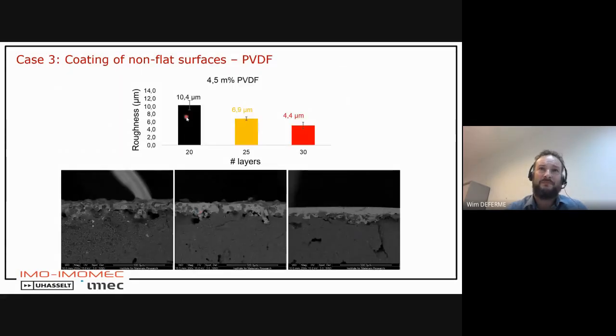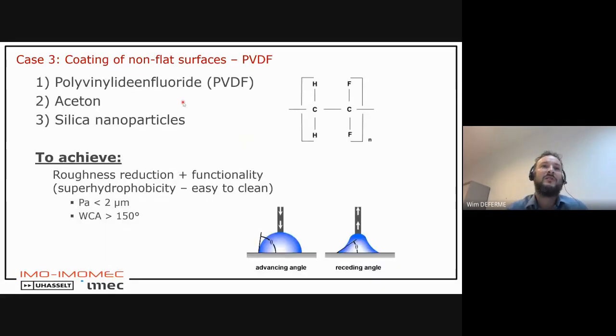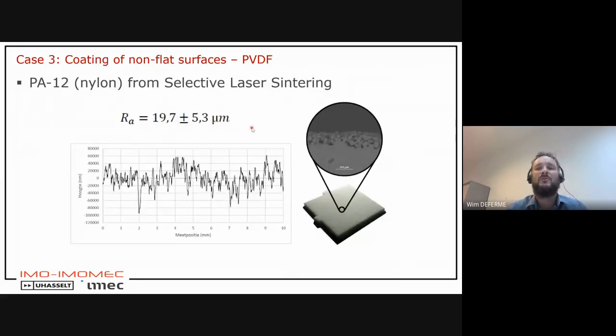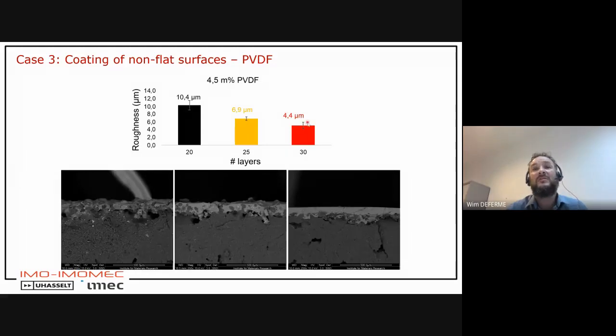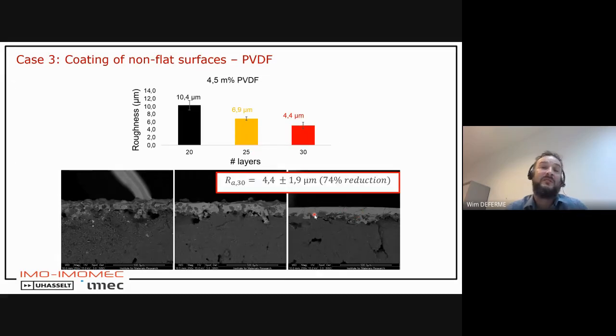And if you look at the results, if we only use PVDF, 4.5 weight percent PVDF in acetone, we could achieve, after 30 layers, a roughness of 4.4 microns, where you saw in earlier slides that the roughness was around 20 microns. So going down to 4.4 microns is nice. And here you see SEM images where the PVDF is penetrating a bit in the top area of your 3D printed part, and in the end getting very smooth layers that completely cover the 3D object. Achieving 4.4 microns is a 74% reduction.